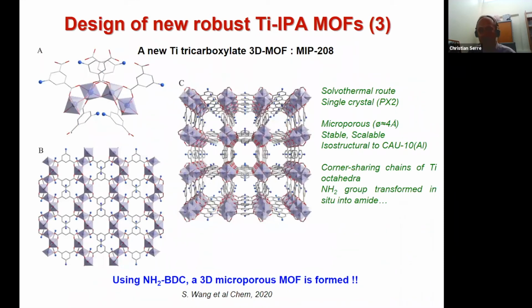In parallel, in the same system, but just changing the ligand to amino isophthalic acid, we could obtain this other structure. This time it's not an oxocluster, it's a chain-based material with corner-sharing, cis-sharing chains of titanium octahedra. And this forms a 3D solid with channels of a few angstrom in size. It is associated with the aluminum counterpart material. And what is noteworthy is that the initial NH2 group is transformed by an in situ amidation, because we use a formic acid or acetic acid mixture to make the material.